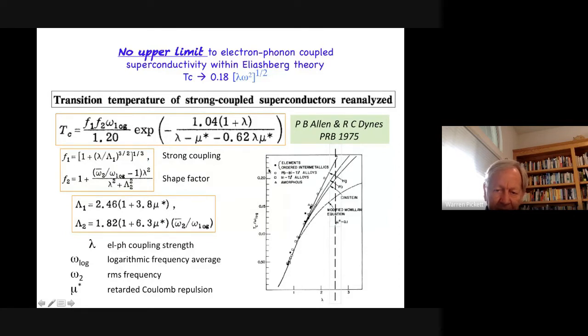And so that was one of the big messages. Here's the expression. One of the big messages of this paper is, within Eliashberg theory, there's no upper limit to the electron-phonon coupled superconducting critical temperature. As lambda gets large, something else may happen. It may change the structure. Well, that does happen. But within the pure theory, if you can keep this in a favorable structure and just increase lambda, which you can never do, TC will continue to go up.